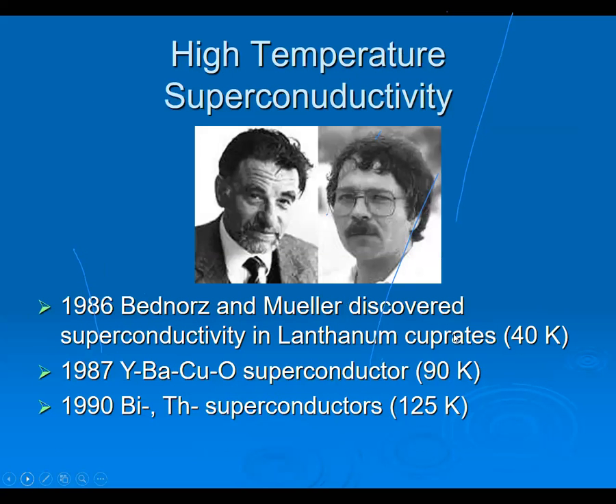But it was around 86, 87 when Bednorz and Mueller discovered superconductivity in a cuprate, that is, an oxide. Then you had YBCO and later the bismuth compounds. Typically 125 to 150 Kelvin is the highest temperature, I believe, which they also have to be stable. So this is the record which was achieved. And the advantage is that because they are above 77 Kelvin, the coolant which you use can switch over to liquid nitrogen.